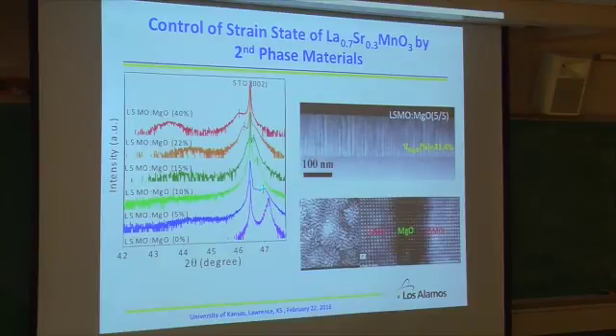For example, this one is the LSMO peak. The MgO peak is over here. If you look at the X-ray diffraction, you see, depends on the ratio, you can systematically shift the peak. You shift the lattice parameter. That's really the strain effect.